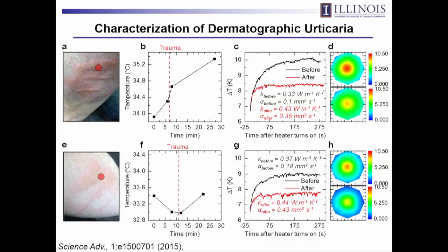That's macrovascular flow. You can also measure microvascular flow, where you're measuring the aggregate effects of flow through lots of blood capillaries. And the best way to see that is in the context of this dermatographic urticaria. Basically, you take your forearm, you slap it, it creates a red region at the point of trauma. You can see the temperature goes up, which sort of makes sense because you have enhanced blood flow near the surface of the skin. But what's even more interesting is you see the effects of increased thermal conductivity associated with the increased blood flow. So the steady state value of the temperature increase for given thermal power input decreases substantially before the trauma and after, and that's due entirely to the increased blood flow.